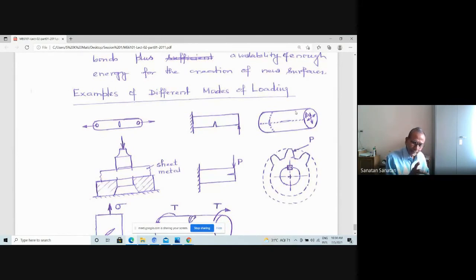This punching, blanking, look at that. There you have the punch at the bottom, the sheet metal at the center, and the punch at the top. When you press the punch, the edges of the punch are pushed into the material, and that finally gives rise to cracks near the tool edges. Those cracks move in the vertical direction and meet each other to separate the material, and that is the punching process. So punching is a mode 2 type of crack propagation.